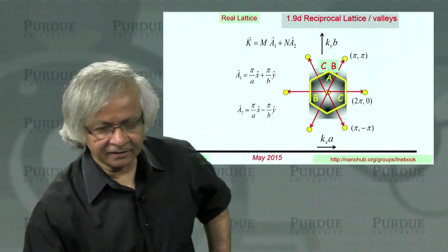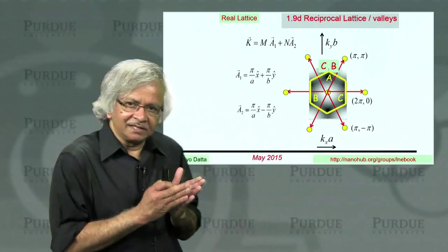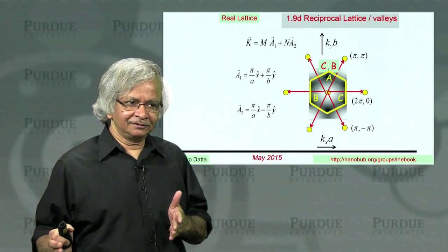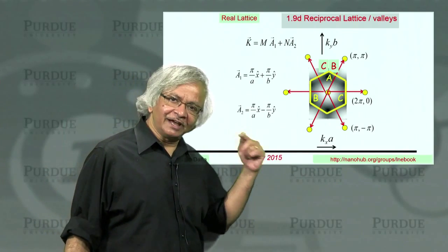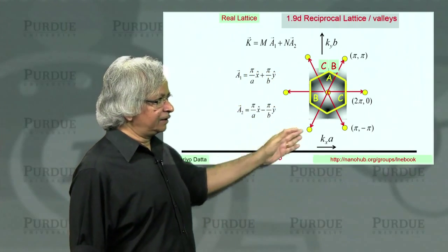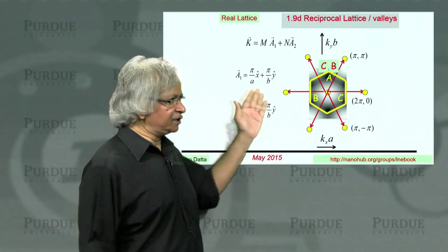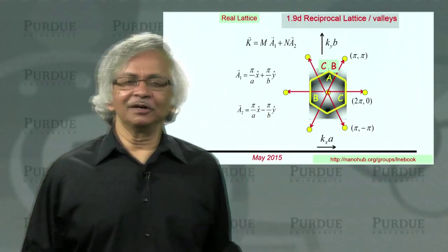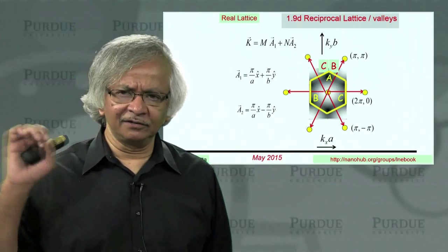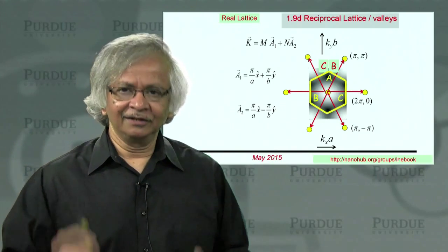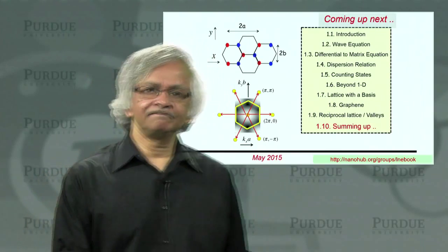Why? Well, because graphene not only has the 2 spins in parallel, but also has the 2 valleys in parallel. And the point to note is it's 2 valleys in parallel, not 6 valleys, it's 2. And the argument, of course, why it's 2 is what we just went through. But the point I was trying to make is, although the argument is fairly mathematical, it has a very direct, experimentally verifiable consequence, namely the ballistic conductance.